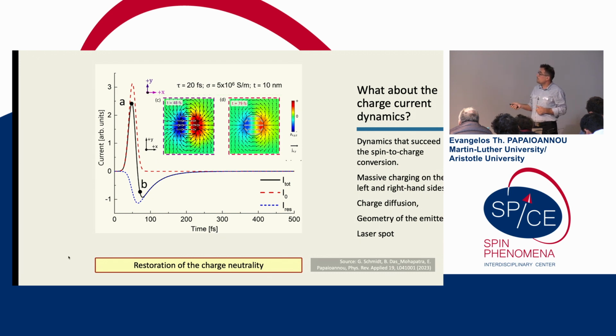So if you make a simulation, and here is the laser spot, and here we plot the charge current density along a specific direction, you see that there is a massive charging at the edges, left and right hand sides. And after some time, this massive charging diffuses, and in principle, if you see here, after some time you even have a backflow of the current, and here you have even a backflow inside the spot where you illuminate.